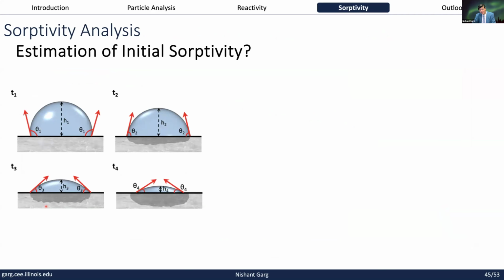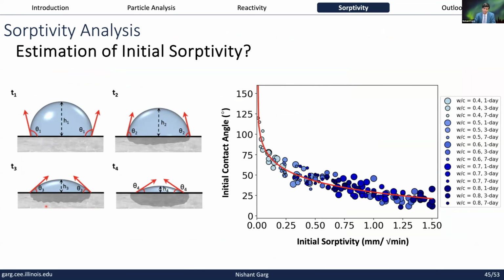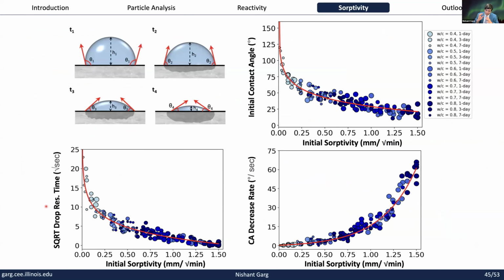Then we wanted to see, can these droplets actually help us understand this initial sorptivity, which takes several hours to measure? It turns out when we measure a range of mixes with different water cement ratios at different curing times, we find that the contact angle actually has some correlation with that initial sorptivity. In fact, when we also correlate the different parameters of the droplet dynamics with that sorptivity, we find some very interesting correlations.